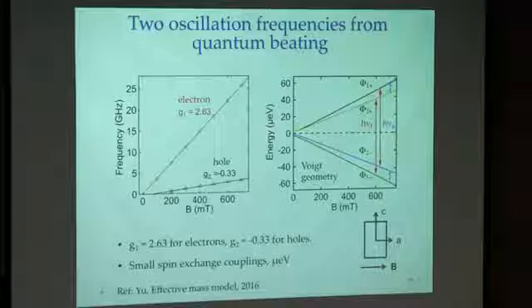So there's also a small exchange coupling. This is not exactly linear, right? There's a small bending at low magnetic field, and that explains a little bit of negative offset here. So this is not some artifact. It's real because we've measured many samples. There are cases where this negative offset is even more, like it goes about here. But still, the exchange couplings are on the order of microelectronvolts.